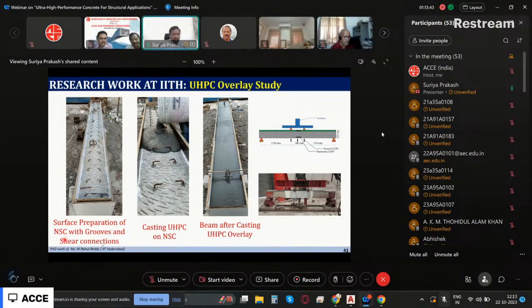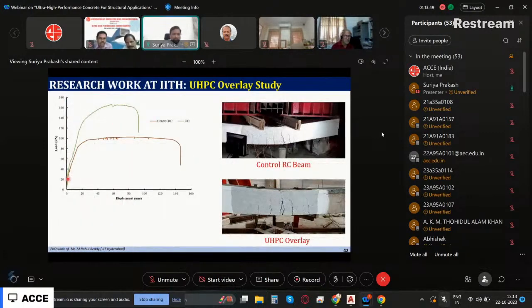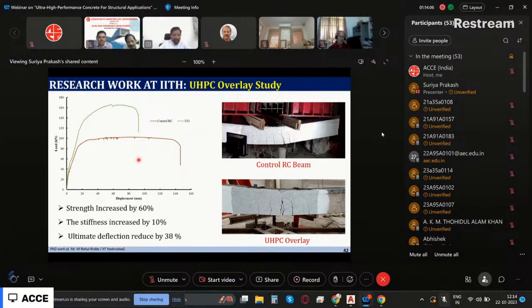This is again one of the PhD students' work, and we tested this strengthening. You see here, this is a beam that was without any of this overlay, and UO stands for UHPC overlay. The moment I put overlay, you can see that strength increased from 100 kilonewton to 160 kilonewton. Stiffness also increased, and also the ductility at failure was not very high.